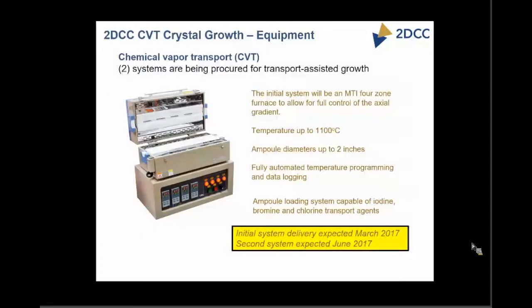When we decided to specify this, we decided to go with a 4-zone furnace. Typically, you often use a 2-zone furnace. This furnace will have 4 zones to allow for complete control of the axial gradient between the hot and cold sections, both in terms of the temperature differential and the gradient. We're hoping to be able to use this to manage the transport of the materials in an efficient way.